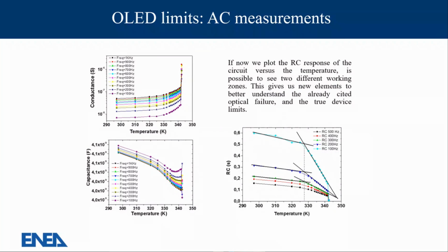And here, excluding the series resistance, we have this kind of behavior, as I said before, that goes every time in the same way for the conductance, but also the capacitance will change at different temperatures. If we take the reverse of the conductance, so we analyze the bulk resistance of our device, and multiply it with the capacitance, we have the three zones, highlighted another time. The first zone is before the transition mechanism, the one in the middle is, as before, due to the transition mechanism, and another is when the device will fail.